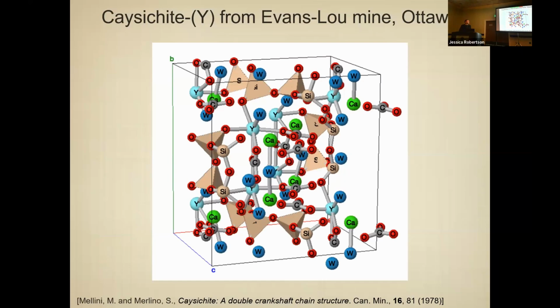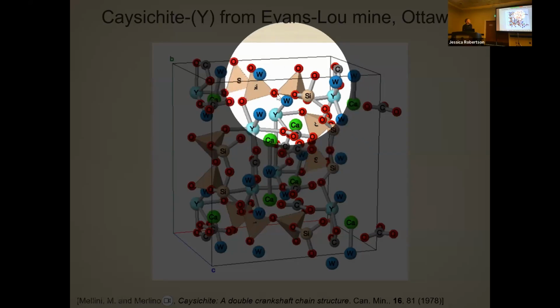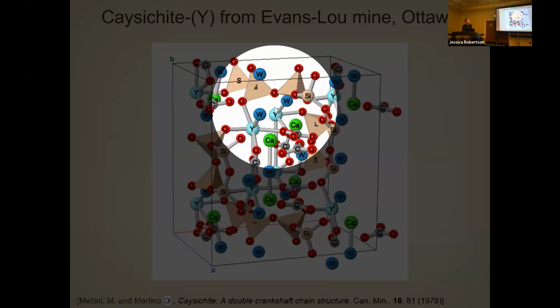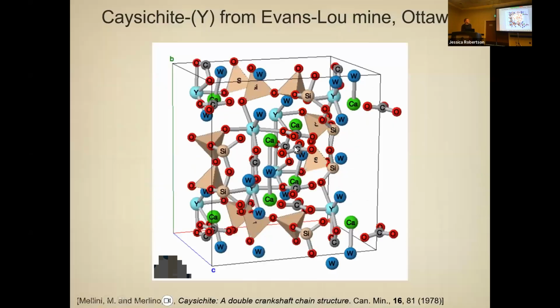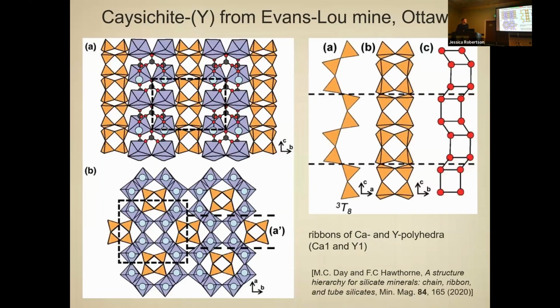The crystal structure is fairly complex, and it has these two distinct sites. There's an yttrium site, there's a calcium site, and then what's hanging out all around, which holds this together, right? You have these very close in vicinity, strongly charged cations, and you have water and carbonates. The water gives it sort of space, and the carbonates are structurally important to hold it together. So it's a complicated structure, and that was also why the original publication of this was quite an elaborate discussion.